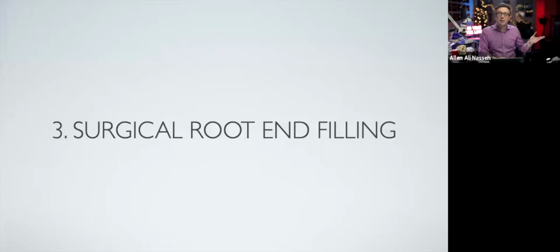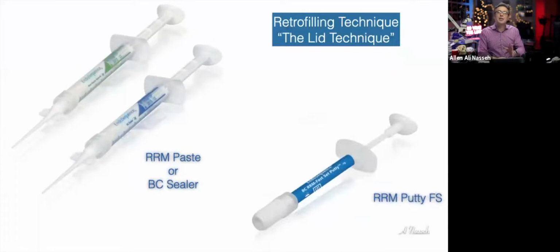We obviously knew with MTA, but the problem with MTA was that it would wash out over time, and it was difficult to apply. It would take a long time to apply that mud-like material to the end of the root. Biodentine was slightly better. What's nice about a technique that I've helped develop here for the specific application, and that's basically the genesis of